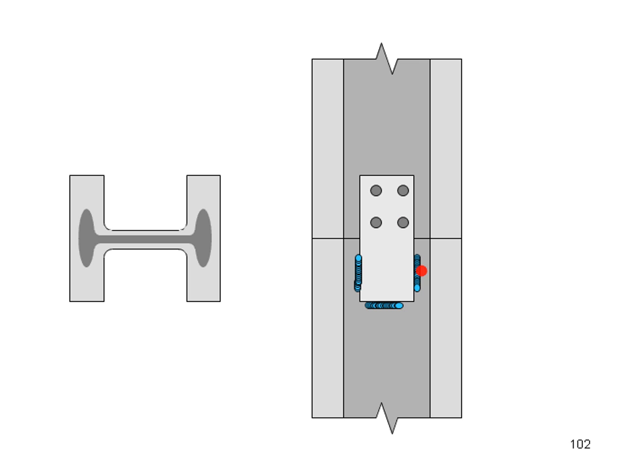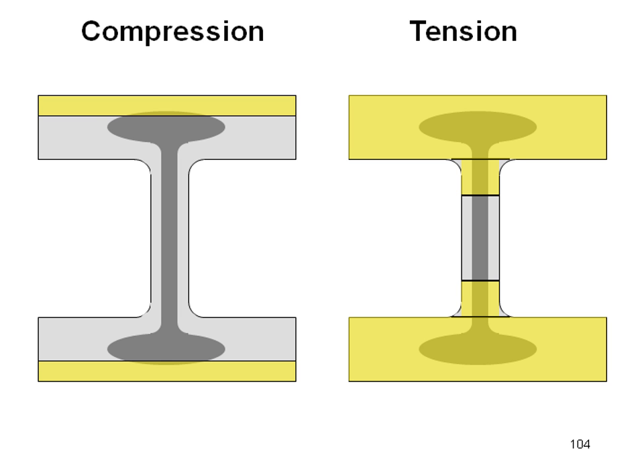And then for the partial joint penetration groove welds, I would have a bevel, but that bevel may not go into the core region of the shape. So it's very conceivable, and in fact, experience showed that we could come up with compression welded connections on these jumbo shapes, and we had no problem. But when we came up with the detailing necessary for a tension joint, we started to see some of these cracking tendencies.